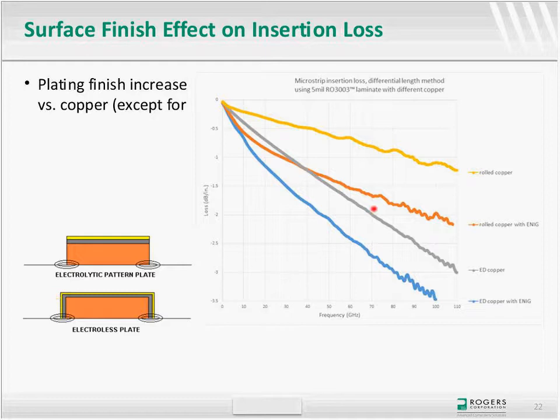So what you'll see here is that when you have the copper versus the effect of the electroless nickel, ENIG, electroless nickel immersion gold, you can see the impact on this particular circuit. In this case, it's 5 mil RO3003, so a Dk 3 material with loss tangent of 0.001. You can see the impact that you will have once you add that to it.